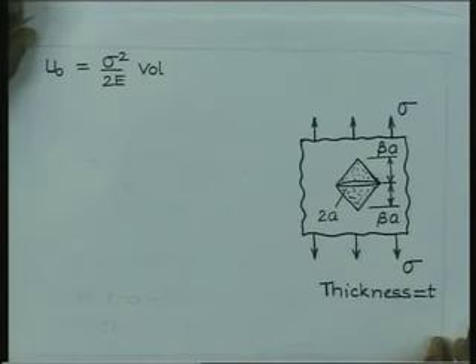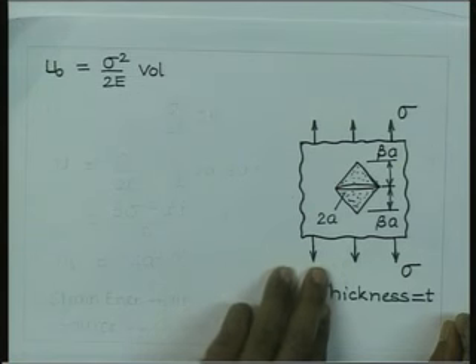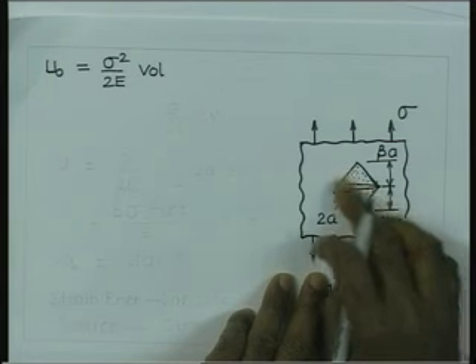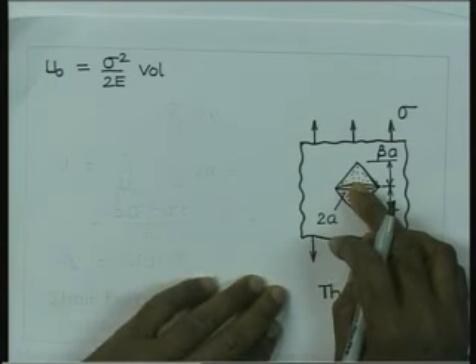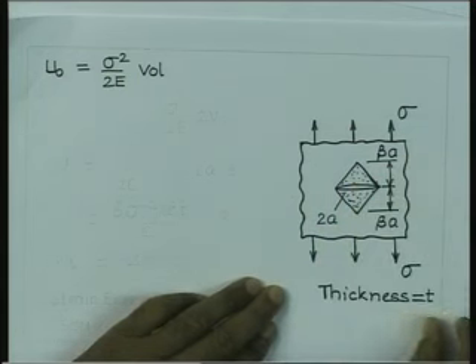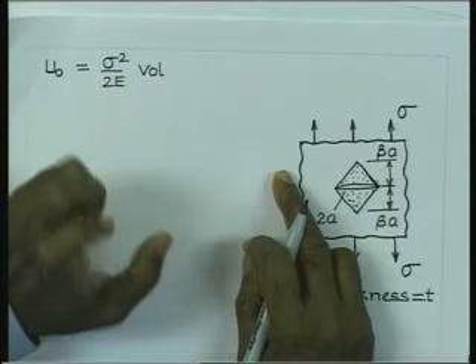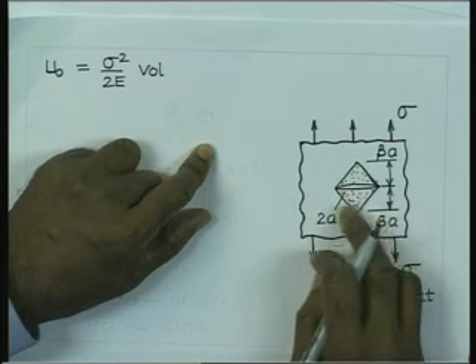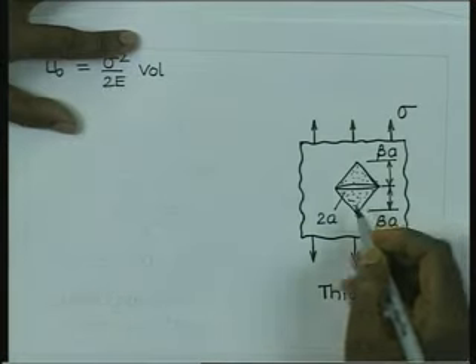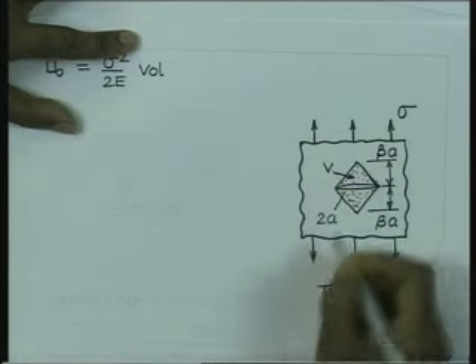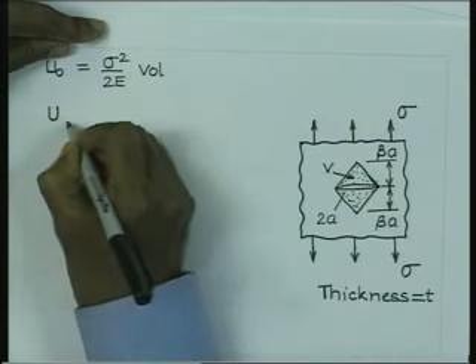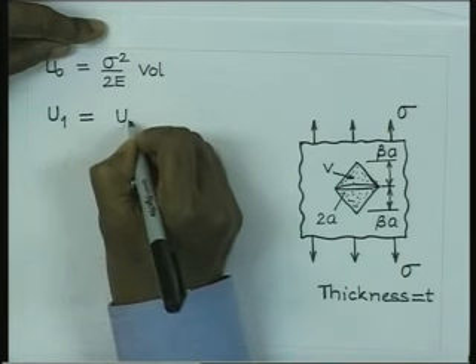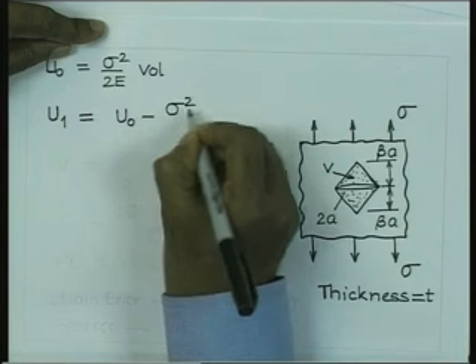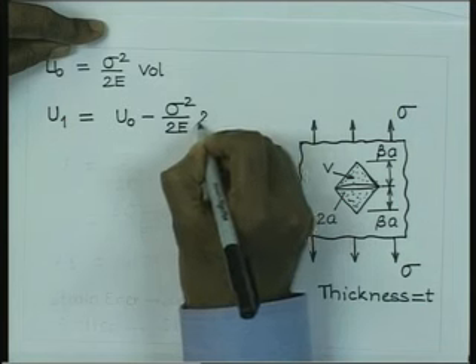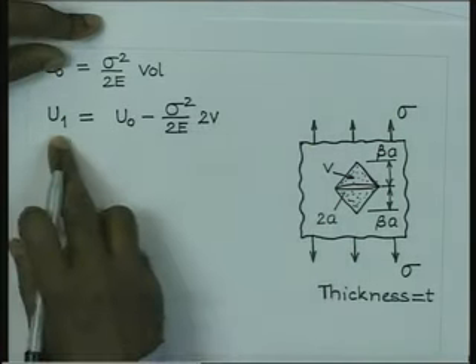Then the difference in energy between the two cases: in the first case, without the crack, the whole body is available. In the second case we have the body with a portion which is free of any stress and strain. Therefore, the energy in the second case with the crack can be written as the strain energy of the earlier state minus the strain energy stored in these two triangular regions. If the volume of the triangular region here is V, then the energy in the second case is equal to U0 minus sigma square by 2E, the strain energy density, multiplied by 2 times V.